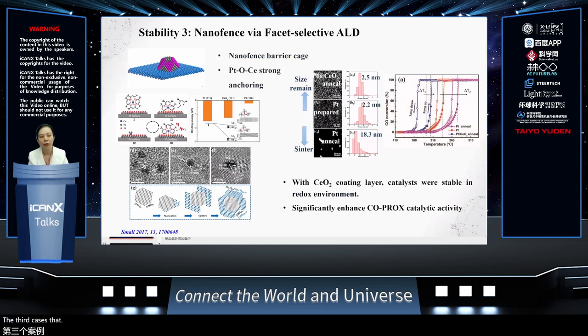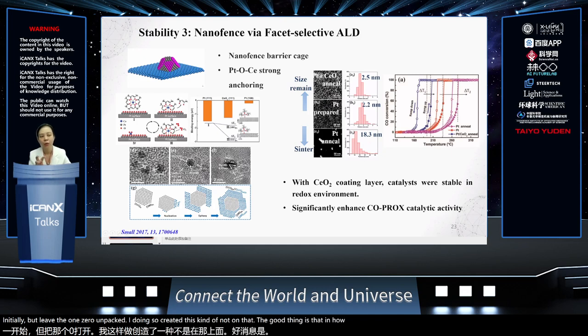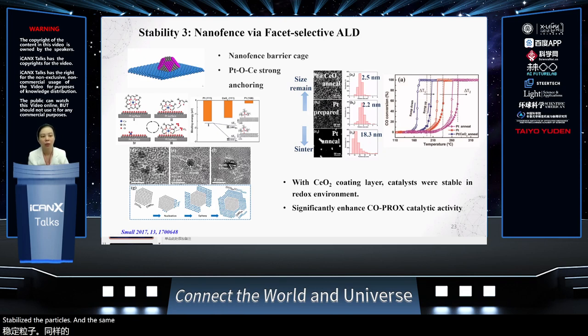The third and fourth cases that I want to show you are utilizing the inherent selective processes. Basically, we are doing this kind of inherent deposition on one facet but not touching the others. This has been achieved through the different binding energies and reactions initially. What happens is that they have a very big barrier difference on platinum 111 and platinum 100. Because they are different, we are actually able to cover one side, like 111 initially, but leave the 100 intact. By doing so, we created this kind of knot on that. The good thing is that it helped to stabilize the particles, and at the same time, it enhanced activities.